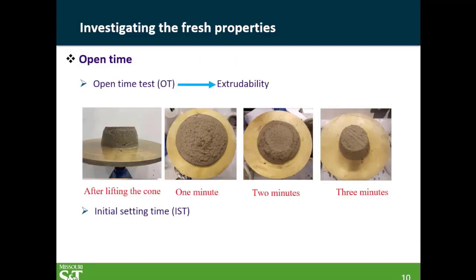So let's start looking at the open time. Open time is very important for extrudability. As we heard today, there is not yet a strict standard for developing 3D printing. So what we use over here as an indication for extrudability, we just use a mini slump. We prepare different mixtures, and then for each mixture we measure mini slump until we have 0 slump, and we recorded this time as the extrudability time.